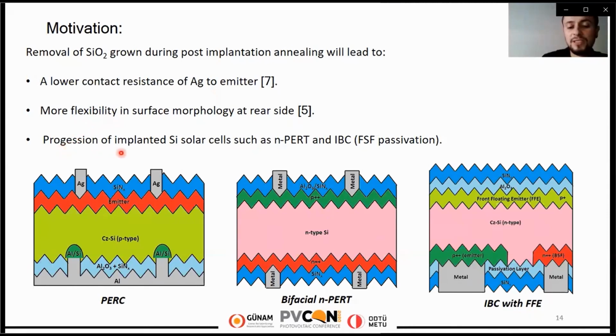Lastly, the passivation of N+ with only nitride instead of a silicon dioxide and nitride stack will lead to progression of other types of implanted silicon solar cells, such as N-PERT and IBC. For example, bifacial N-PERT solar cells have a P+ emitter at the front side, and an alumina and nitride stack provides a superior passivation on the P+ emitter. If we have silicon dioxide at the P+, then the passivation quality of the alumina and nitride stack will diminish. It is the same for IBC solar cells. When we have a front floating emitter at the front side, silicon dioxide may diminish the effectiveness of the alumina and nitride passivation stack at the front side.